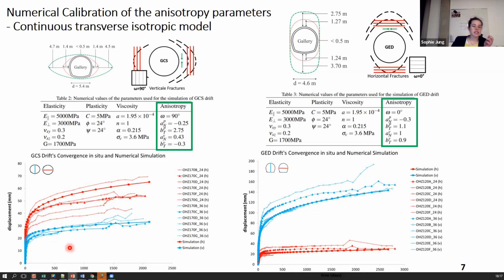So as you can see here, in bold, you have the result of the numerical simulation, and the other curves represent a measurement of in situ vertical and horizontal convergence. There are many curves because many sections of the drifts were measured. And so the parameters of anisotropy are different between the two drifts, as the fracture density and orientation are not the same in both fractured zones. So while the convergences are well reproduced, the parameters of anisotropy are not clearly linked to the fractures yet. At least it's not easy to understand their physical or mechanical value.